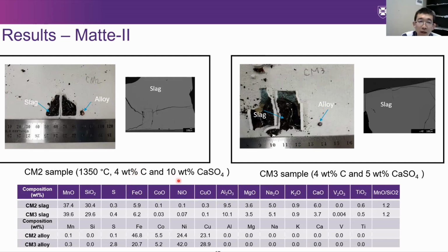We just tried 10% for calcium sulfate addition, and also 5% of calcium sulfate addition. And then we get a fully molten slag at low temperature, which has a very good separation of alloy from slag. And from this, the table shows the composition of slag and alloys.